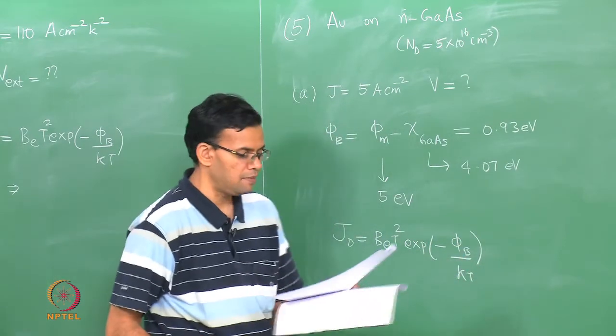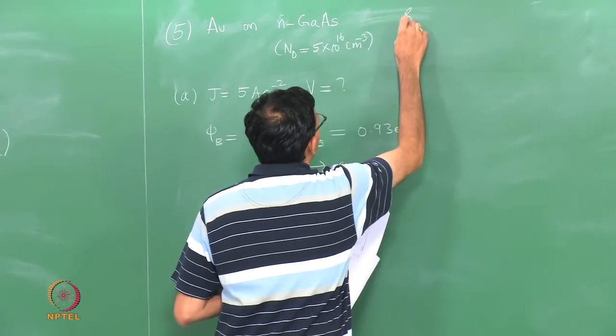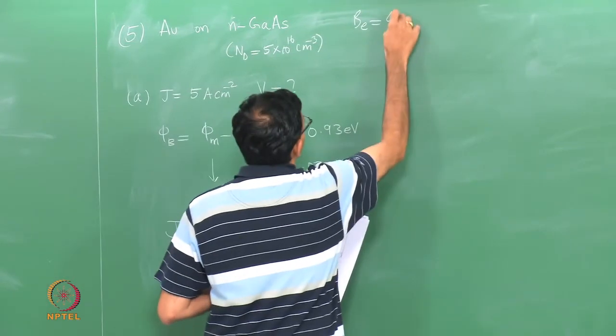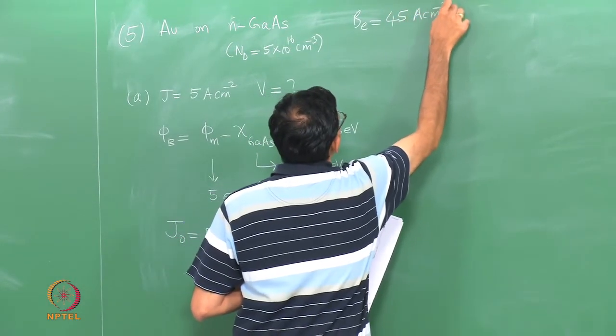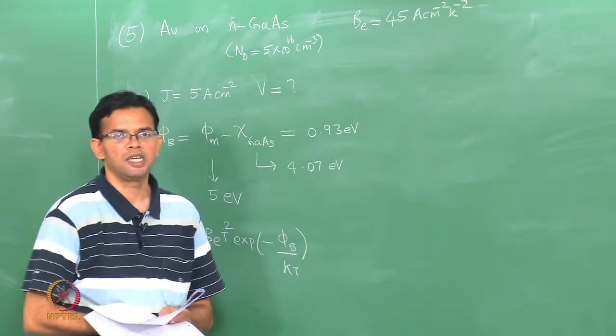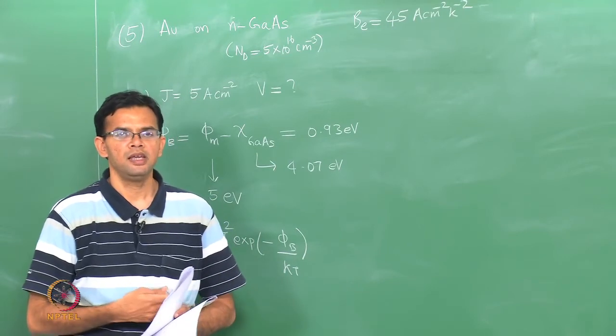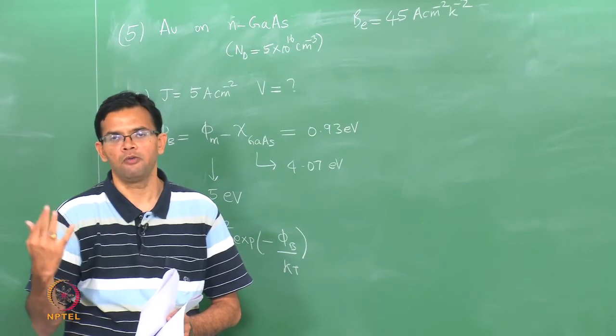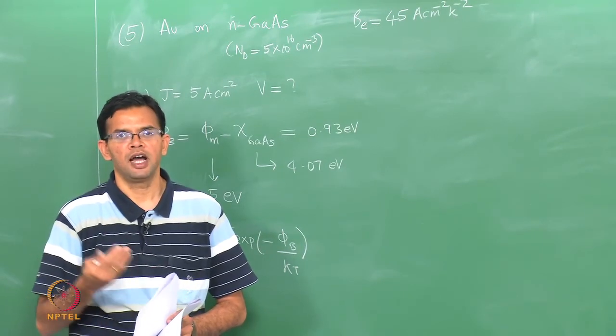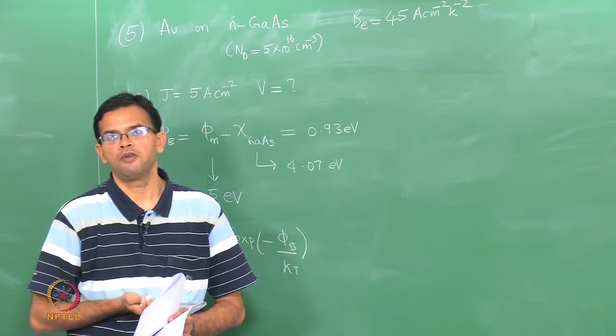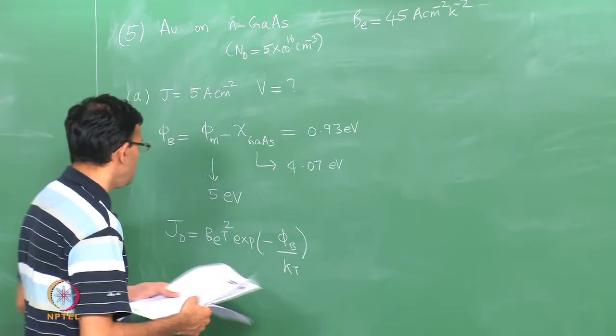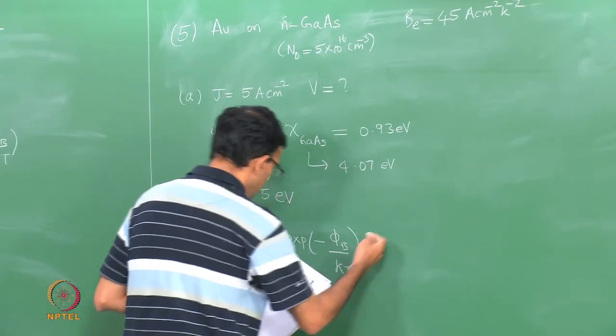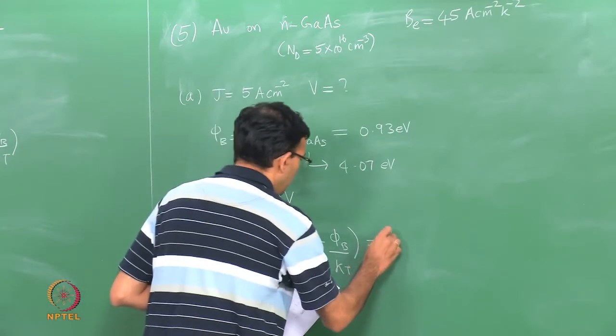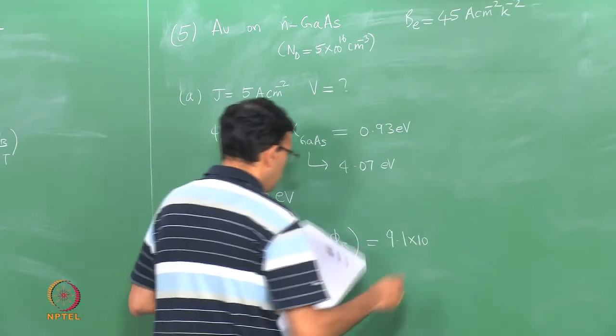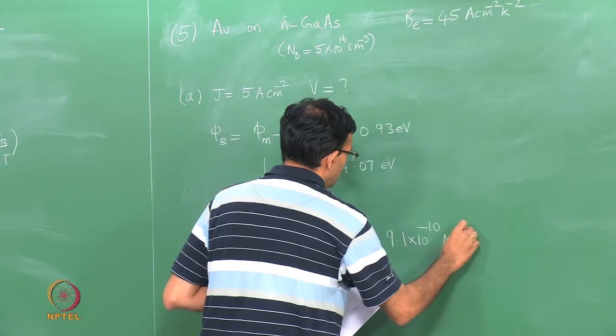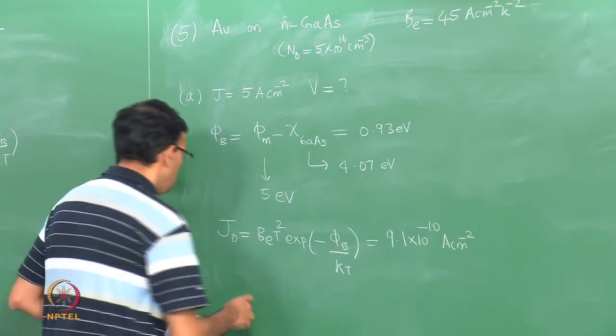Again, for the gold and gallium arsenide interface, we have the values for B E. B E is equal to 45 amps per centimeter square per Kelvin square. B E is not only a material property, it also depends upon what facet of the material you have. So, whether you have a 100 plane or a 110 or a 111, that will also affect the value of B E. J naught is a number we can calculate, all the numbers are known. This is nothing but 9.1 times 10 to the minus 10 ampere per centimeter square.